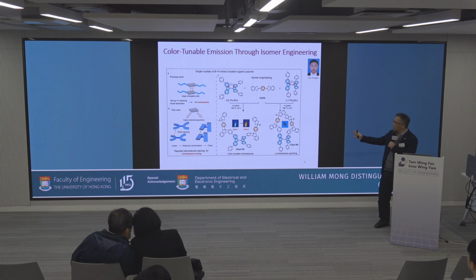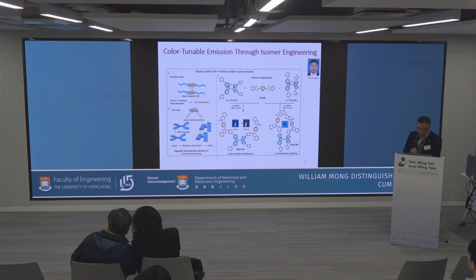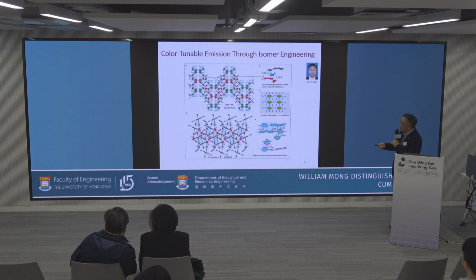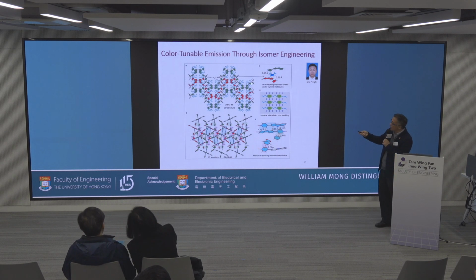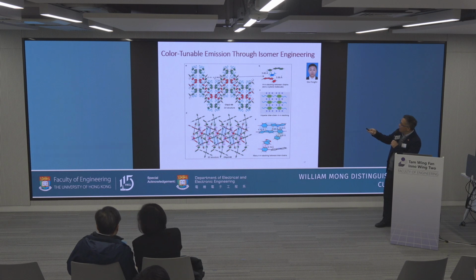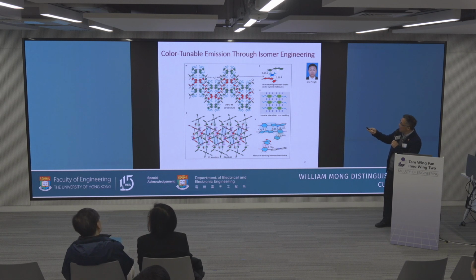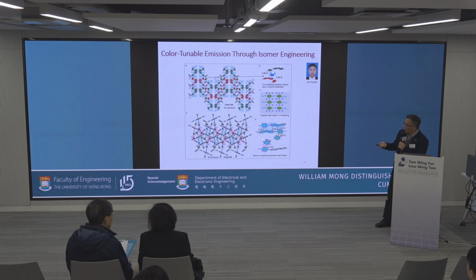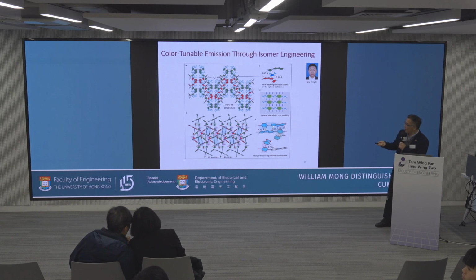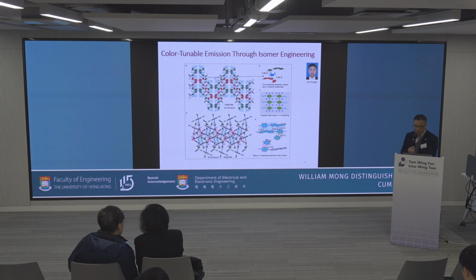Right? Since we have the crystal here, it's easy for us to solve the crystal and look at what's going on here. Looking at the crystal, you can see that for the 3-6 position, inside we have the solvent, and these 2 polymer chains almost have no interaction with each other. However, for the bottom one, the polymer chains have strong pi-pi interaction. So for the bottom one, the emission will be quenched because of pi-pi stacking, but for the top one, there is almost no quenching. They have the emission as shown here.